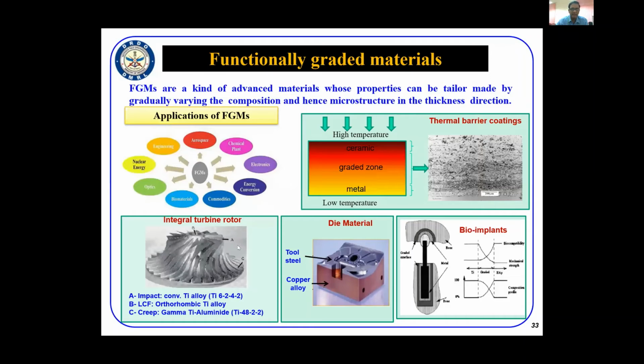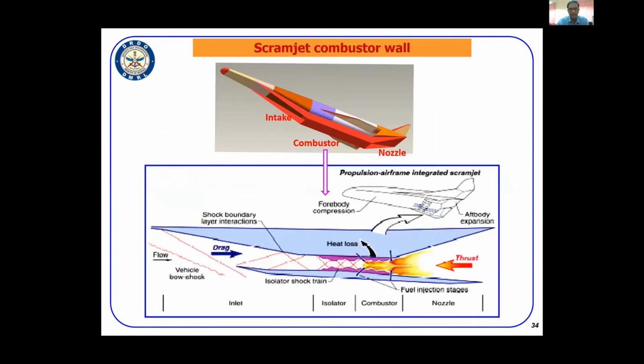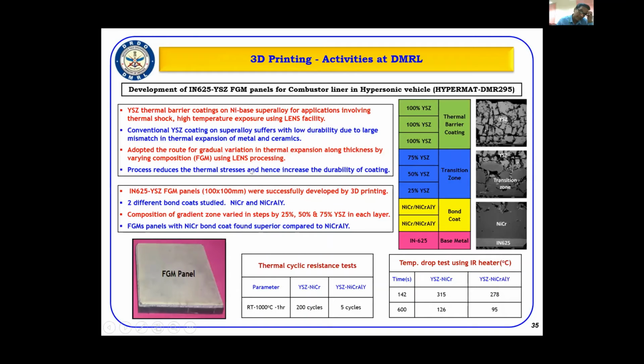And this is the functionally graded material. These are again a kind of advanced materials whose properties can be tailor-made gradually using the composition and hence microstructure in the thickness direction. So these functionally graded materials we have developed for hypersonic applications, and here is a little detail on one of the activities we have taken up for this FGM component. Here, YSZ thermal barrier coatings on nickel-based alloys, where the initial base material is nickel-based, and these components involve very high thermal shocks and high temperature exposure using the LENS facility.